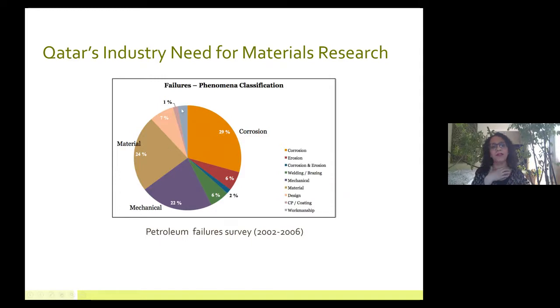So when we look at it, we see that 24% of their failures are due to poor material selection. So they selected material for an application they thought would work, but it did not work. Then 29% of these failures were due to corrosion, but that's also associated with material. Always material and corrosion work together. So the material didn't do well in terms of corrosion properties or mechanical properties. The materials' mechanical properties were not good enough for the application.